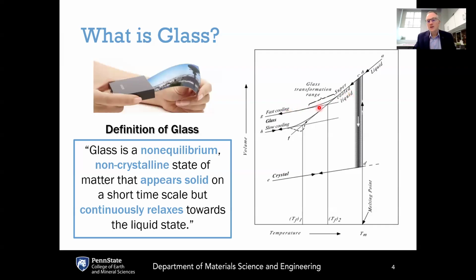What's the difference between a glass and a supercooled liquid? A supercooled liquid is a metastable equilibrium state. A glass is a non-equilibrium state that you're not going to find anywhere in a phase diagram because phase diagrams only deal with equilibrium phases. And the only reason that we observe it is because it is kinetically frozen in.